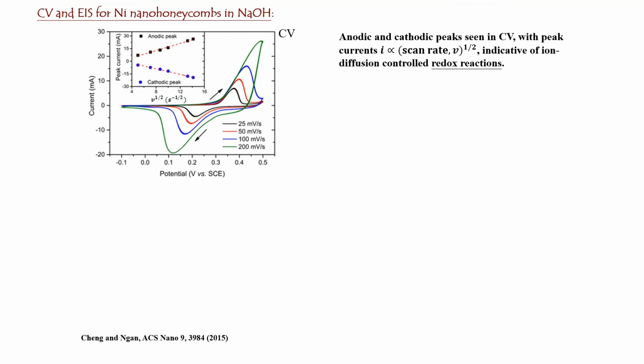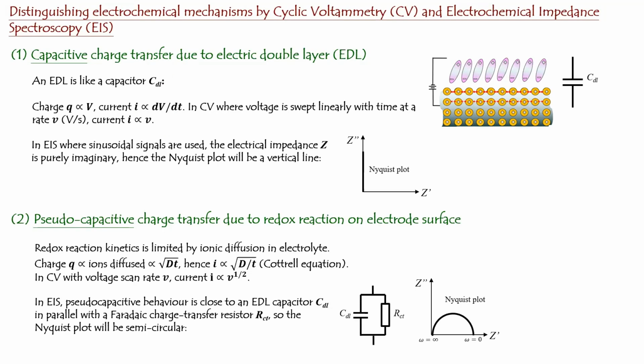So the first thing that we observe is that, also I forgot to mention, there are other characteristics as well. For the EDL, the charge is proportional to voltage. That's what a capacitor will do. Okay, so if you differentiate that equation, dq/dt becomes your current. So the current will now be proportional to the voltage rate. So that would be the characteristic of the EDL. If you charge up this material with a constant voltage rate, the current should be proportional to that.